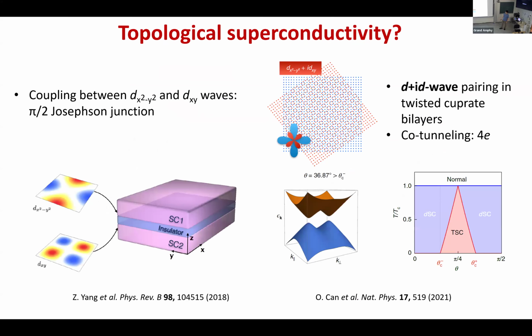However, there is this prediction that the magic angle for twisted cuprate is at 45. That means you have a D-wave in one layer, you rotate one of them 45 degrees, and it becomes very similar to this d_xy order parameter. So if the two layers couple together, and you treat this whole system as a single block, then it has a new pairing, a new order parameter, which is d+id.